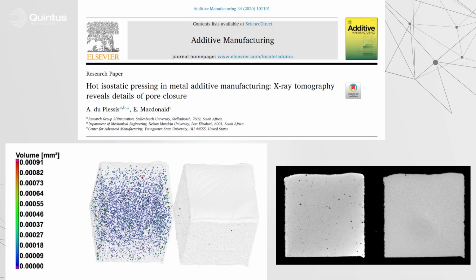What we did is we intentionally created different defect states. So by varying different process parameters, we got different amounts and types of pores inside this material, imaged it non-destructively using CT, and then the exact same cube used in the imaging was then subjected to hipping and then imaged again to exactly quantify which pores close up and which do not close up and how well the hipping works. And the quick answer, you're welcome to read the paper, is it works really great. Only when pores are really near the surface is it a problem.